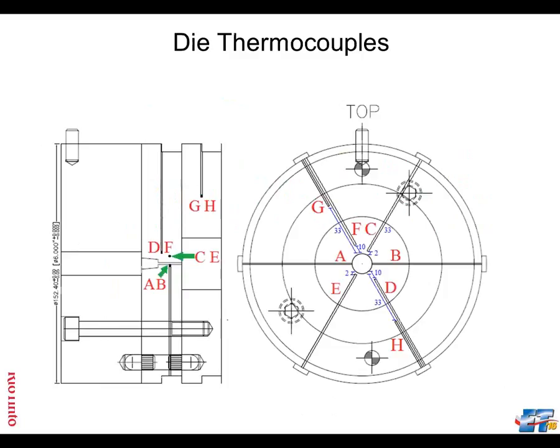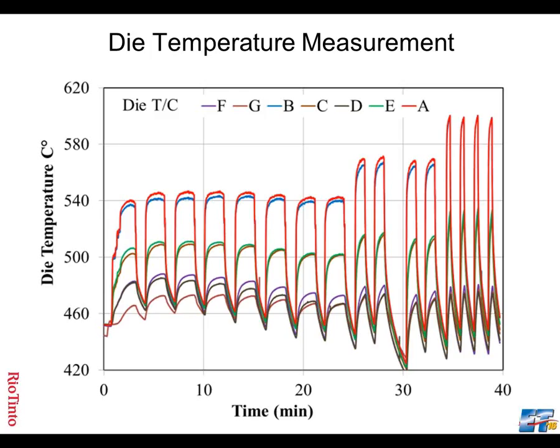The second thing we did was to run this die. The die we used for these tests was a simple half-inch bar. We filled the die with thermocouples and measured temperature, and this is some of the data we got, again with this 16-billet run. If you look at the right-hand side, when we're running at high speed, the temperature at the bearing varies between 440 up to 600.